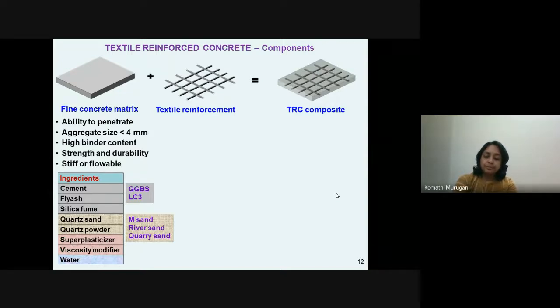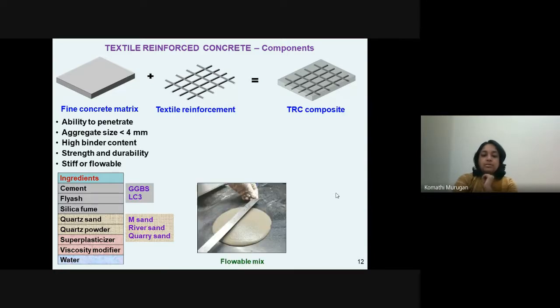Apart from this, what is present as ingredient in the textile reinforced concrete are the superplasticizer and viscosity modifier to control the flow properties, along with water. So what we essentially check in this concrete or the matrix is the flowability of the mix. Suppose if we are using a flow mix, we do the flow test using the mini slump or the flow table to ascertain the properties.